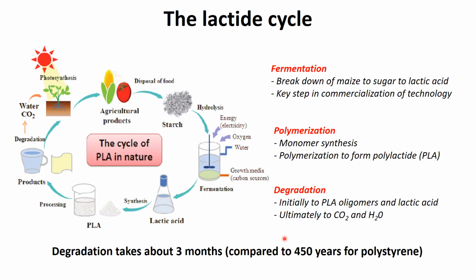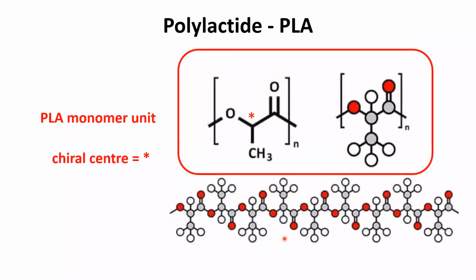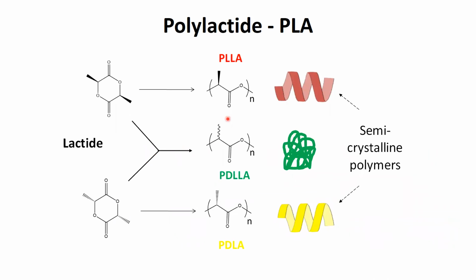One of the big advantages of polylactide is that it also has stereochemistry. This is the monomer and polymer structure of polylactide, and we have a stereo center with this chiral center. So that means we can start to think about how this very simple monomer that can be made from sustainable feedstocks has chirality, which is one of the things we said we'd want because it helps us get added function. And this is just to show you the result of that. Very interestingly, we make the dimer of lactic acid, which is this lactide ring monomer, and we can ring open it, polymerize it to form polylactide. If we have one isomer, the L isomer, we form a helix. If we have the D isomer, we form a helix as well.